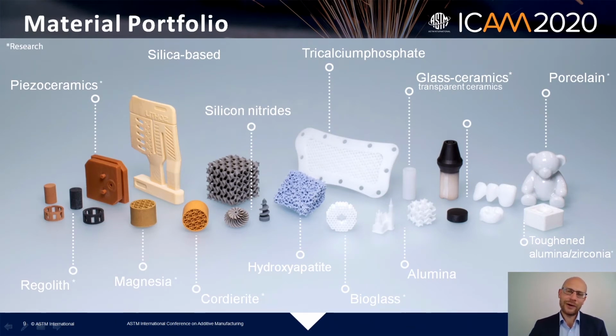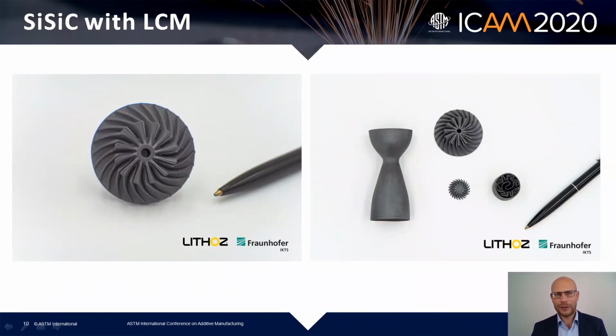Another material very recently is what you can see here, a metal ceramic composite, a silicon infiltrated silicon carbide. Together with the Fraunhofer IKTS, we were able to produce these parts, which you can see here. This is also something very unique in this field. Basically, what we can do, we can use every powder from conventional forming technologies, and it's processed the same way as in conventional forming.